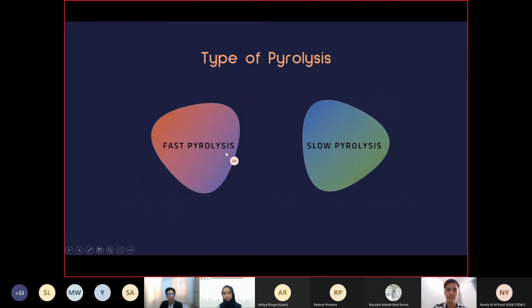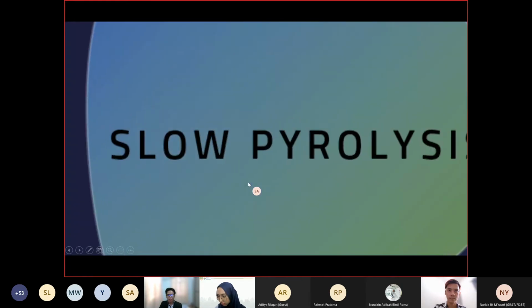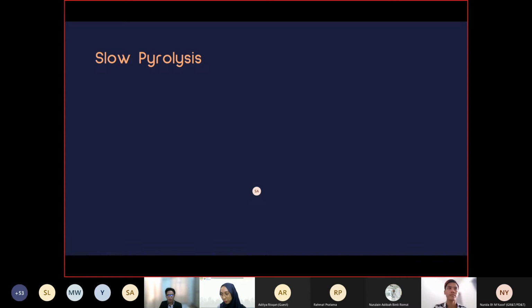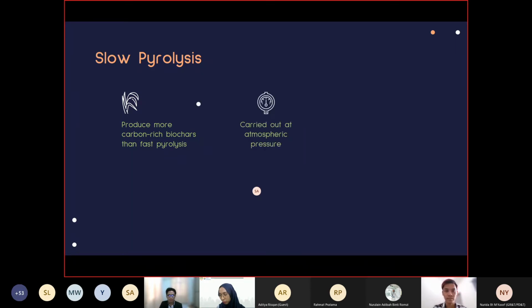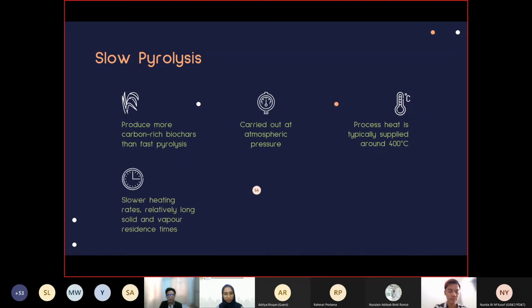The two main classes of biomass pyrolysis are fast pyrolysis and slow pyrolysis. In this process, we focus on slow pyrolysis of biomass, as it can produce more carbon-rich biochars intended for agricultural use, with more reliable and consistent product qualities than fast pyrolysis, which yields more bio-oil. It is carried out at atmospheric pressure, and the process heat is typically supplied at around 400 degrees Celsius. It is characterized by a slower heating rate and relatively long solid and vapor residence time.